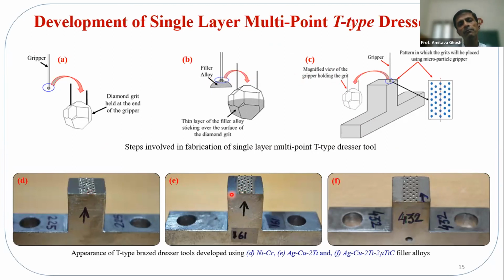Now, the same thing if we use for grinding something else, or maybe we manufacture a wheel where there is a cluster of the grits, rather than the grits being placed in a uniform distribution. So what will happen? The inter-grit pockets will be clogged with debris, and the functionality of the diamond cannot be realized, and there will be a failure of the tool because of that. So we need to place the grit.